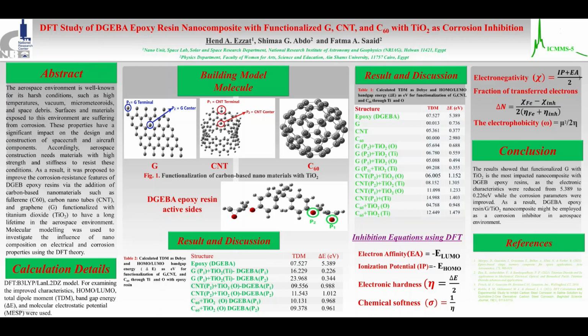density functional theory calculations. For examining the improved characteristics, highest occupied molecular orbital and lowest unoccupied molecular orbital, total dipole moment, band gap energy and molecular electrostatic potential were calculated for all model structures. The results showed that functionalized G with TiO2 is the most impacted nanocomposite with epoxy resins, as the electronic band gap was reduced from 5.389 to 0.226 eV. Also, the corrosion parameters were calculated and confirmed an improvement according to composition. After collecting the studied parameters together, epoxy resin/G/TiO2 nanocomposite might be employed as a corrosion inhibitor in aerospace.